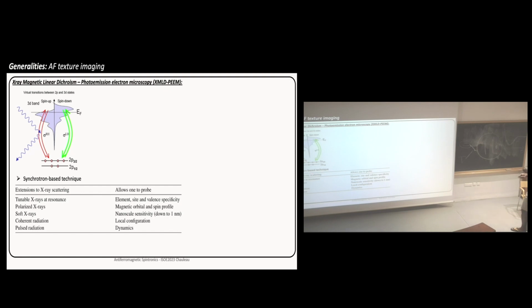So the idea behind this one is that you shine X-ray light, but you shine it resonantly to some electron transition. And most of the time it's the 2p towards the 3d if you have some magnetic ions. The nice thing about this is that you have element specificity. So by changing elements, you have to change the wavelength, and then you can define which kind of atom you want to probe. So that's, let's say, the X-ray part.